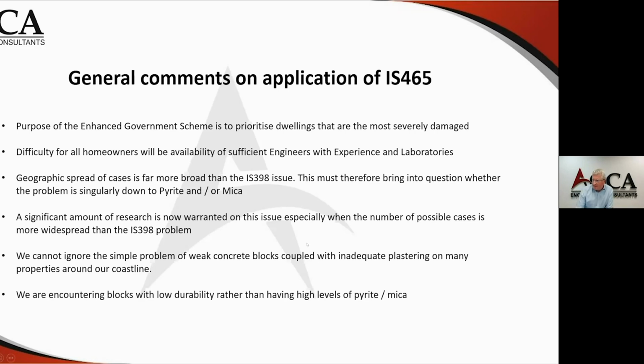That's why I'm saying that a significant amount of research is now warranted on this issue, especially when the number of possible cases is more widespread than the IS 398 problem. We cannot ignore the simple problem of weak concrete blocks coupled with inadequate plastering on many properties around our coastline. Simon will probably agree that I've gone out and looked at a number of properties within counties that are affected by pyrite and with mica. And when I look at it quite carefully and do some testing on the rendering, I don't find any breakdown of the concrete block.